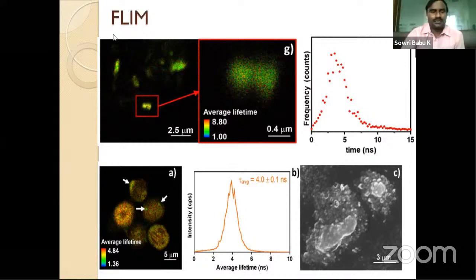Right. So we have a technique called fluorescence lifetime imaging microscopy. In this, you can see, because zinc oxide is a fluorescent material, the moment light falls on it, if a green emission is coming out from it, it appears as green. Okay, so you can see rod shaped structures in this picture, and this is the top view of the fluorescence. So we have hexagonal tips if you see the nanorods from the top of it, and this is by measuring the lifetime. The lifetimes of these zinc oxide nanorods are around 4 nanoseconds, which is in good agreement with the lifetimes of zinc oxide. So that's how we confirm the presence of zinc oxide nanorods by using the fluorescence lifetime imaging technique also.